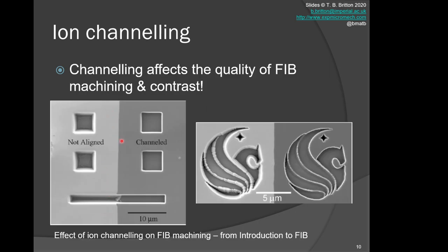This has huge implications. For instance, if you're on-axis in silicon, down the 001 pole, you can get very beautiful, very sharp edges because you get very efficient liberation and sputtering of your material. If you're not aligned and slightly off-axis, you get strong rounding and redeposition, so that changes the quality of the holes you're going to cut. You can also see the relative depth of the cuts is different between the two orientations, and that's important if you're trying to cut shapes of specific depths. You have to be careful to calibrate for the different orientations if you care about how far you've sectioned into your material.